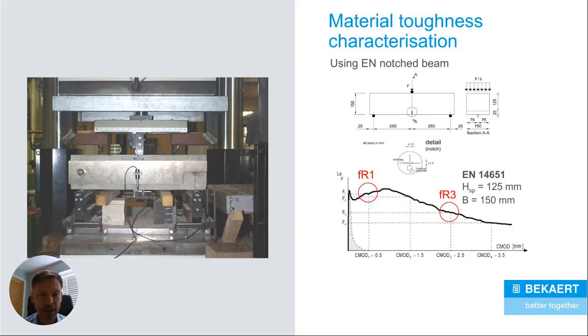What you will see from the graph is that we measure 4 different increments after the cracking. You might be able to make out the lettering along the x-axis of the graph, CMOD. This stands for the crack mouth opening displacement. And what we do is we plot 4 different locations on the x-axis to get FR1, FR2, FR3, and FR4. So these are levels of ductility that are achieved by this sample, reinforced with steel fibres at different increments, different openings of the crack.